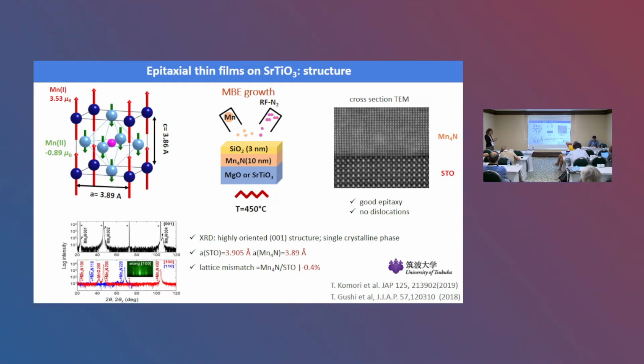But we are interested in thin films. These thin films, as I said, are made by our colleagues at Tsukuba University in Japan. We studied ones deposited on strontium titanate, STO. Their typical thickness is of the order of 10 nanometers, and they are covered with silicon oxide to prevent further oxidation. These samples are made by molecular beam epitaxy.